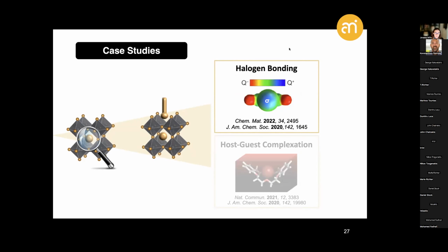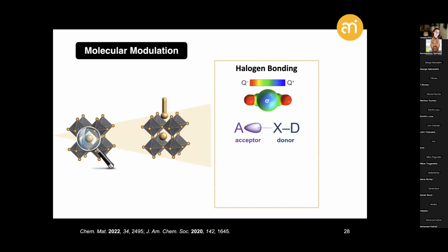Now, when it comes to halogen bonding, this is a type of interaction that some of you might not be familiar with, which motivates me also to introduce it, as it is very closely related to hydrogen bonding, in the sense that it also takes place between a corresponding acceptor, which is a nucleophilic species, a highly electronegative atom like nitrogen or oxygen or halide in this case, and in this particular case, a halogen bond donor, which is, unlike hydrogen, a highly polarizable halogen atom attached to an electron withdrawing core, which permits the formation of an area along this halogen carrying atom bond of relatively positive charge, illustrated here in blue, known as the sigma hole, which is the defining feature of halogen bonding in the sense that it also enables this interaction to be highly directional, taking place only within angles that are very close to 180 degrees,